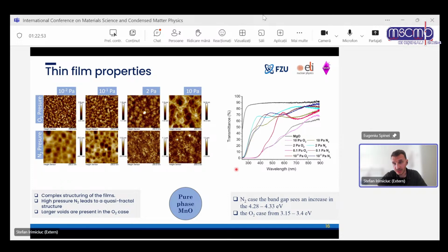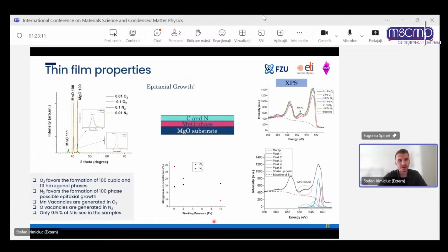And we see that also from optical transmission. People have done calculations, and this is the manganese-rich case. This is the band gap that we can find for MnO, and this is the oxygen-rich case. So we can confirm well with other theoretical calculations. We perform X-ray diffraction to check the single-phase orientation. Also, there's a possibility of epitaxial growth, but we need to check with cross-section TEM for these films. But definitely there's the MnO phase in our films, regardless of the gas. So this time the gas phase reaction didn't do what we wanted.